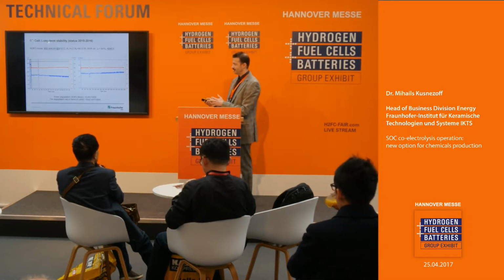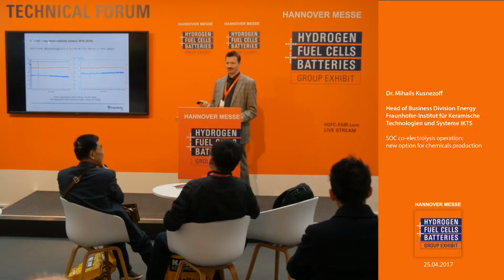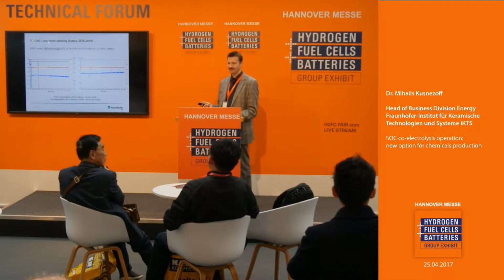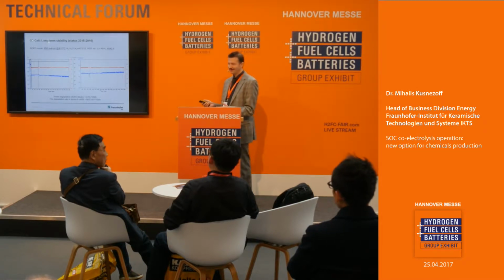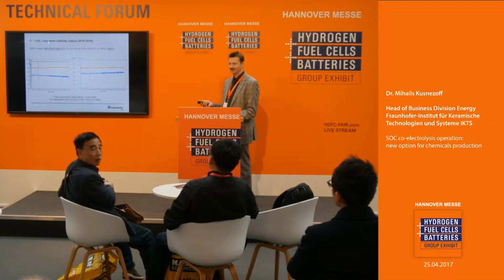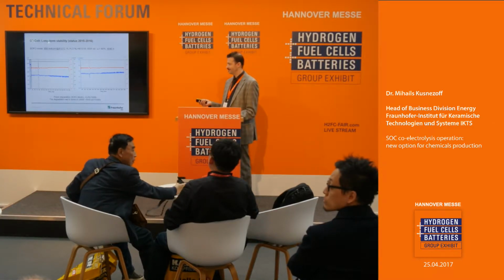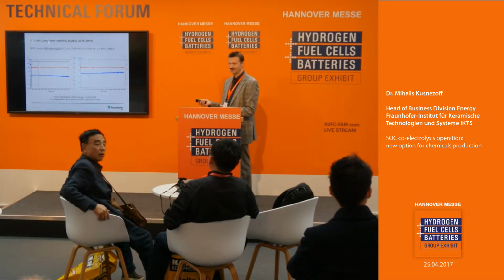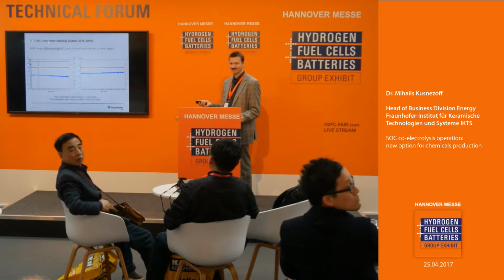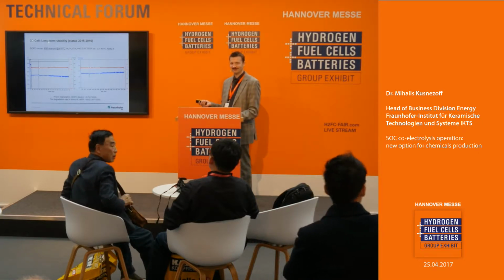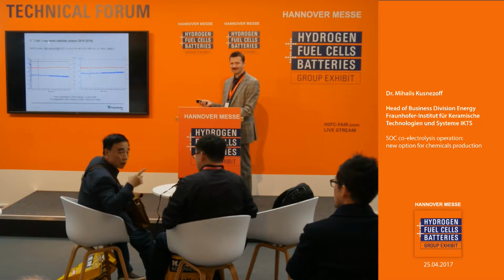Here you see the graphs of testing of our G3 cell for SOFC operation, and you see that even scattering of the data is more than the degradation we can measure. So for this reason, we are running the cells 4 times, more than 4,000 hours, to determine the degradation rate.